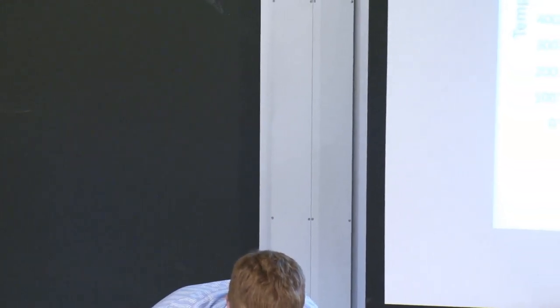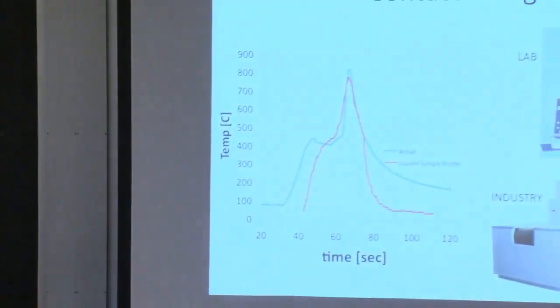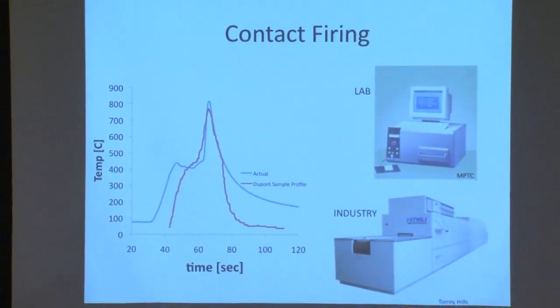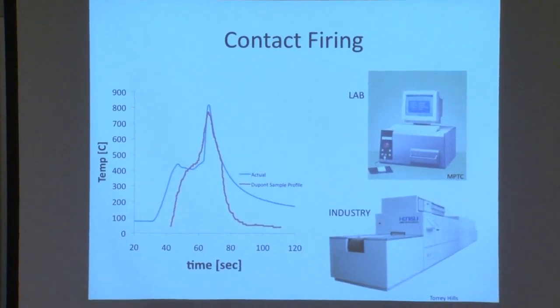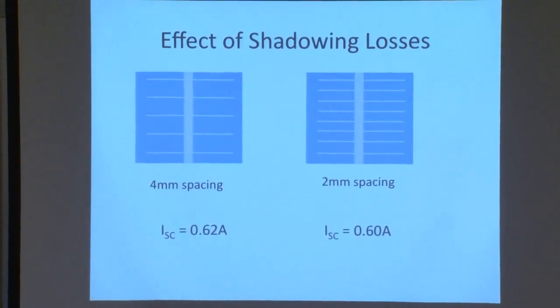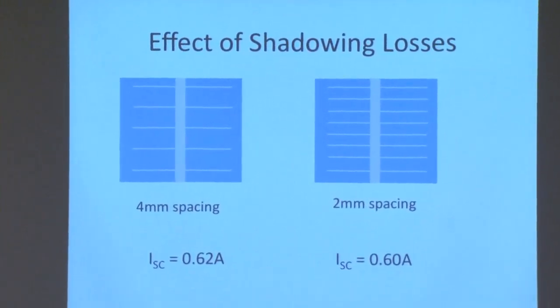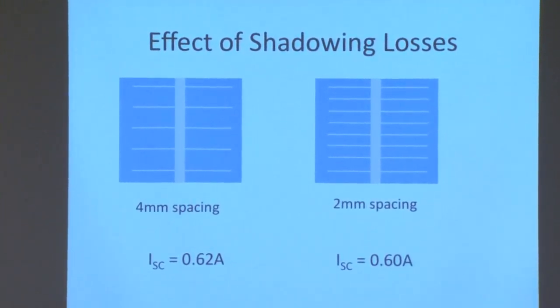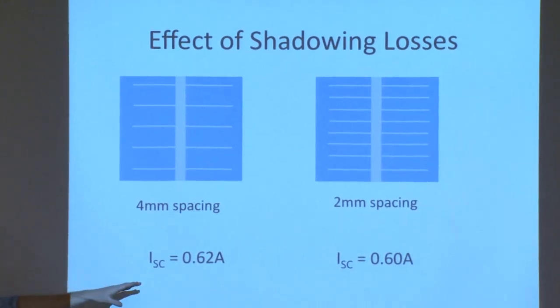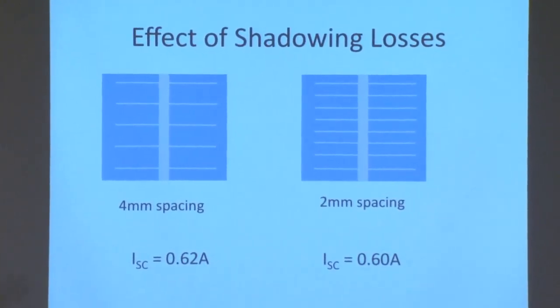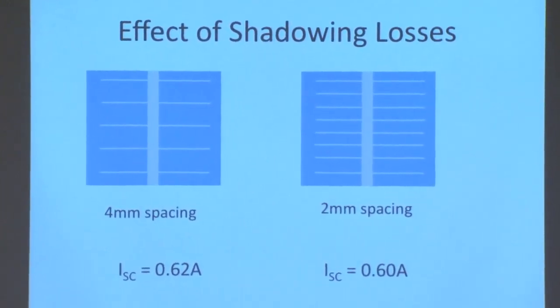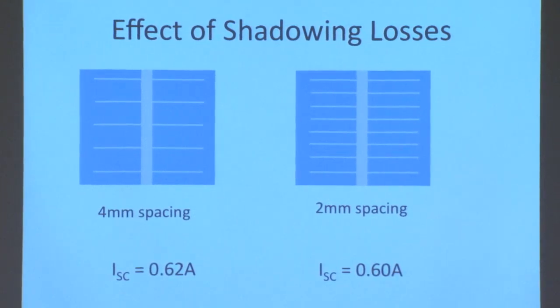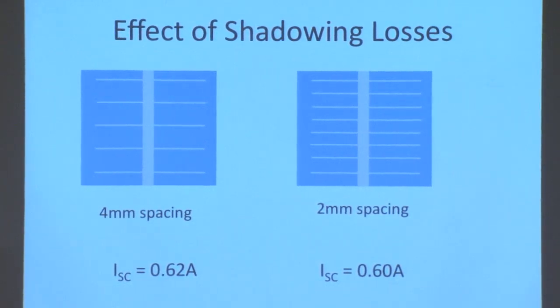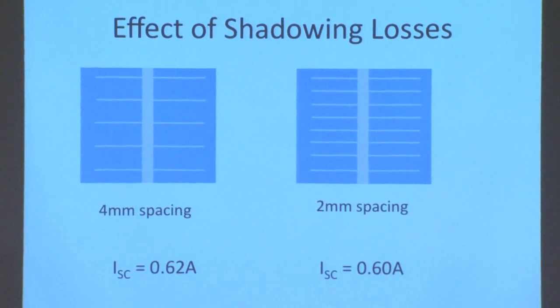So anyhow, that just kind of gives you what I was working on over the weekend trying to get these cells fired. So I aggregated a lot of the results and tried to make sense of what was going on. I think I showed some of you different firing temperatures and the fill factors we got, and there was just noisy data, so I couldn't get any real trends. The best trend I could find was that if you take the median of all the short circuit currents of the cells and you look at the ones with 4 millimeter and 2 millimeter spacing, the 4 millimeter spacing has a slightly higher short circuit current, presumably due to shading losses. If you look at the relative areas that each of these cover up, you would expect a 4% increase. This is about 3%. So I'll take that as fact. It's certainly within the noise and the error of the number of samples that we have, but I thought it was interesting nonetheless.